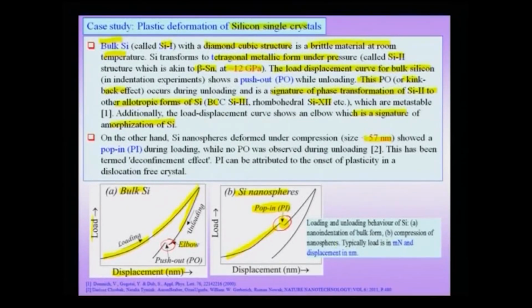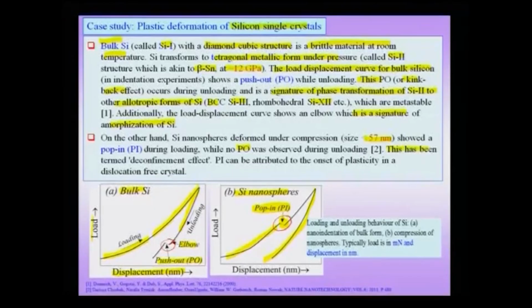But there was no pop out or push out effect, which we had seen in bulk silicon. So, that part of the curve is smooth, there is no PO effect when I am unloading the silicon. The difference in the nanosphere case is while loading, and this pop in effect has been termed a deconfinement effect, and it can be attributed to the onset of plasticity in a dislocation free crystal. So, clearly there is a very significant difference between loading bulk silicon in indentation and the compression of a nanosphere, and there are important effects, technically called the deconfinement effect, wherein you are seeing the onset of plasticity in a dislocation free crystal.